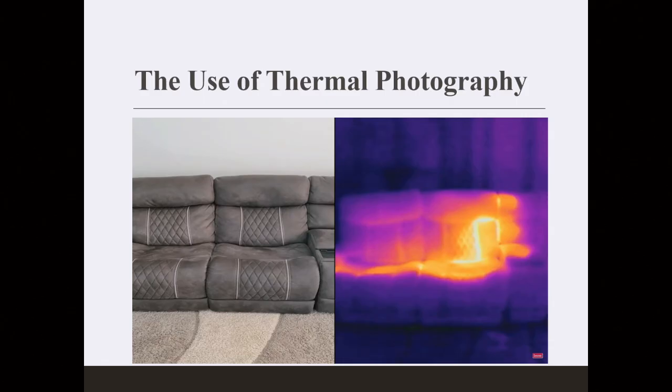This was one of the research projects I did, and they are implementing this at the North Carolina Department of Transportation, where I do research through my university. They attach thermal cameras to drones. When a contractor is pouring a bridge deck, they fly the drone, and the camera captures how the heat is developing.